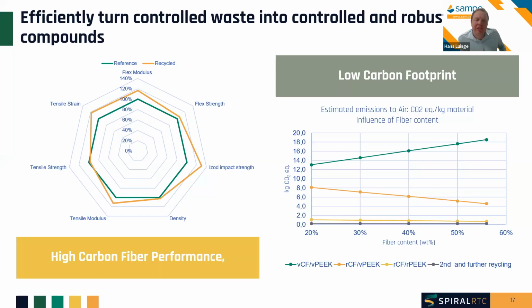So we made our estimations, and that's shown in this graph, and I'll talk you through it, and it should give some tendencies. So it's 4 different lines, where the V stands for virgin and the R for recycled, and you have the different combinations for injection molding compounds of different weight percentages. And on the y-axis is the amount of emitted CO2 per material. If you look at a virgin material, the carbon fiber is quite energy intensive to make. So the higher the carbon fiber loading, the more the CO2 emissions increase.